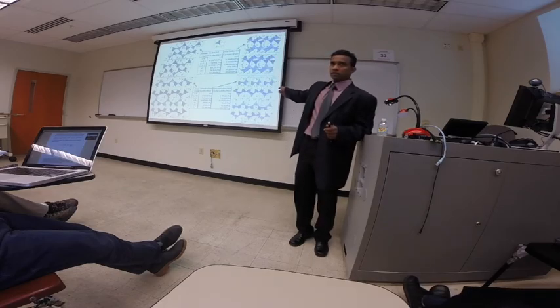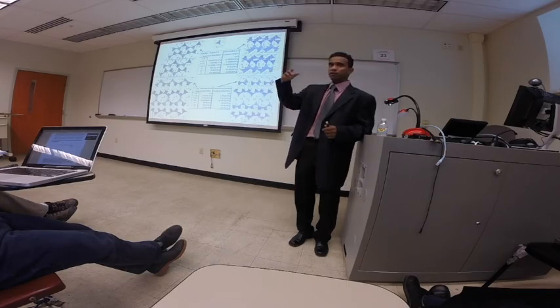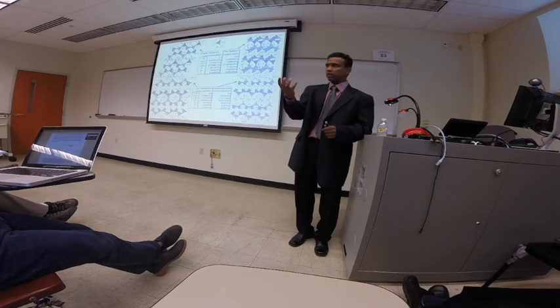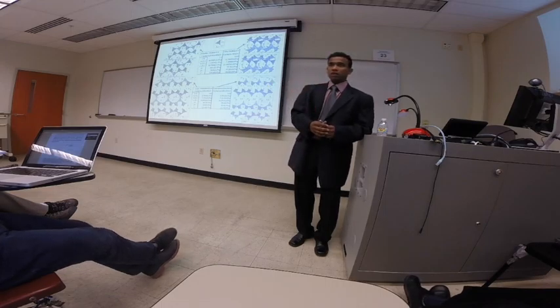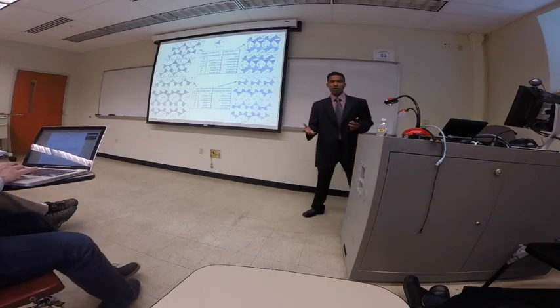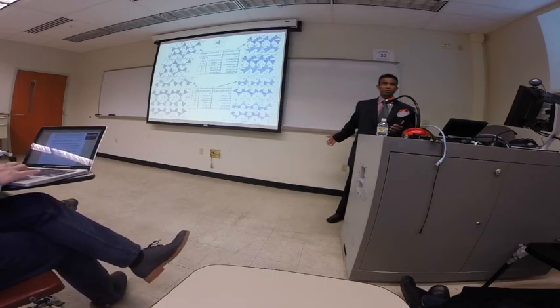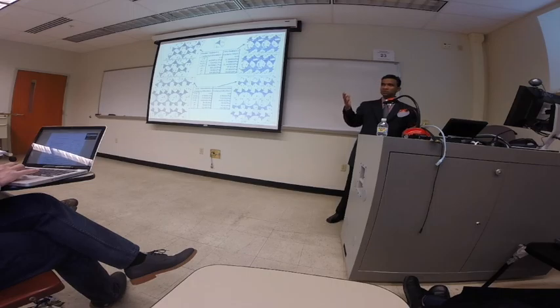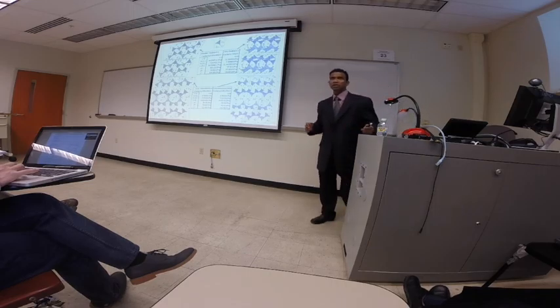And as in the Jennings CM2 model, it still has freedom to have porosity in the cement particle. So the reason why we cannot really say that it's totally amorphous is because you still find some structure in XRD patterns in cement.